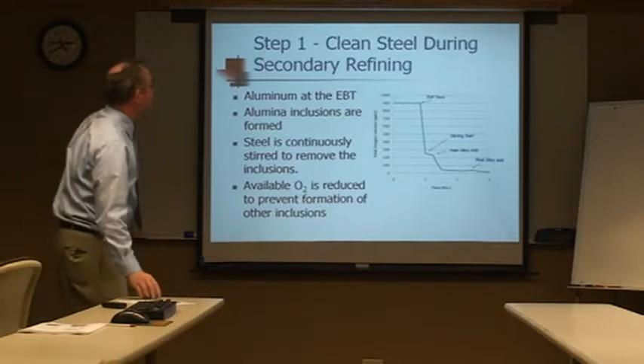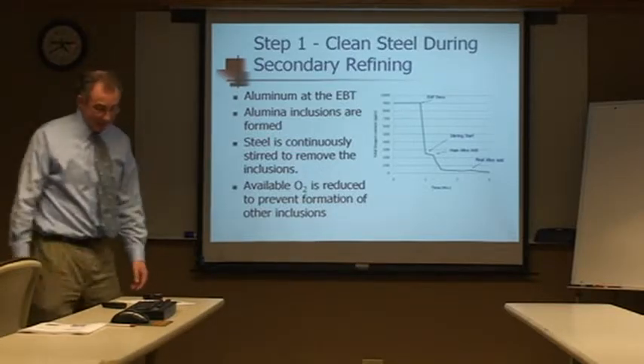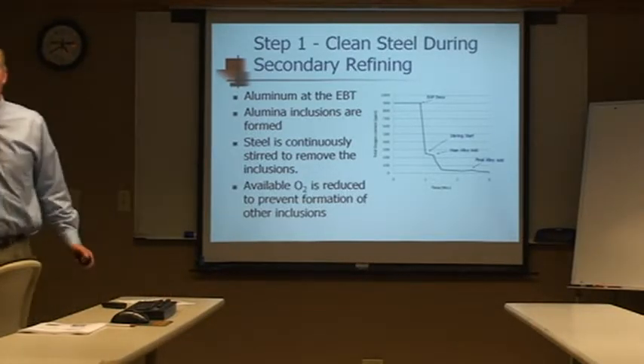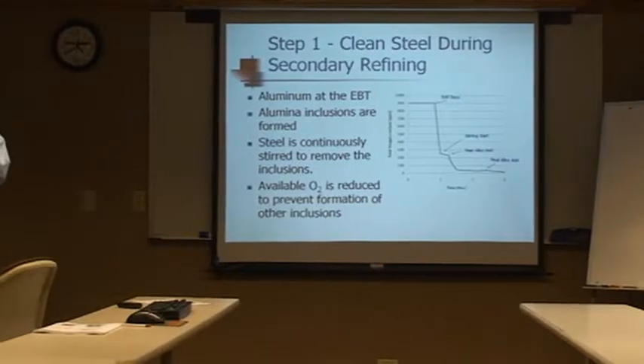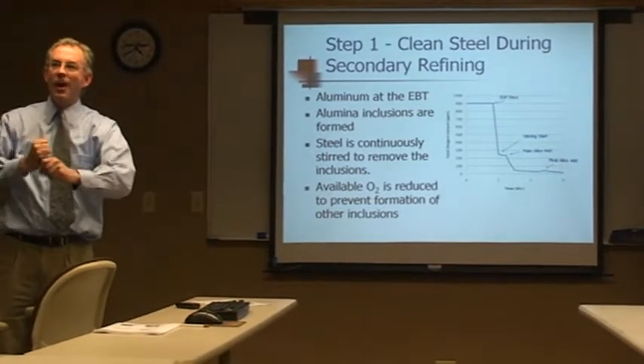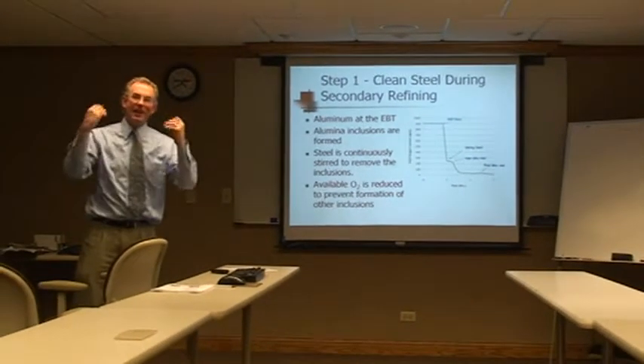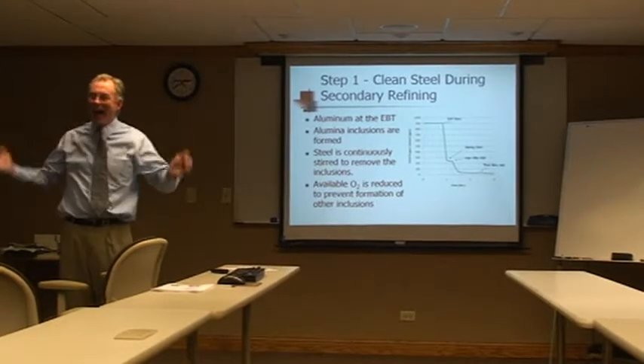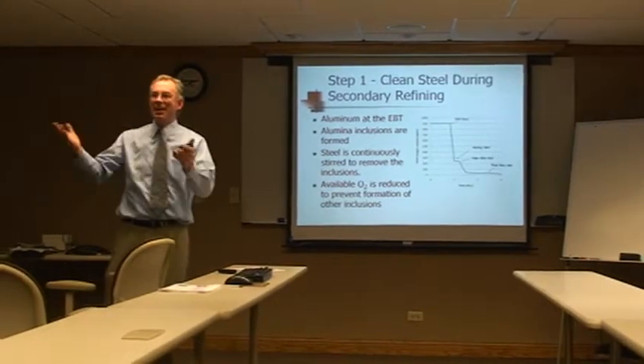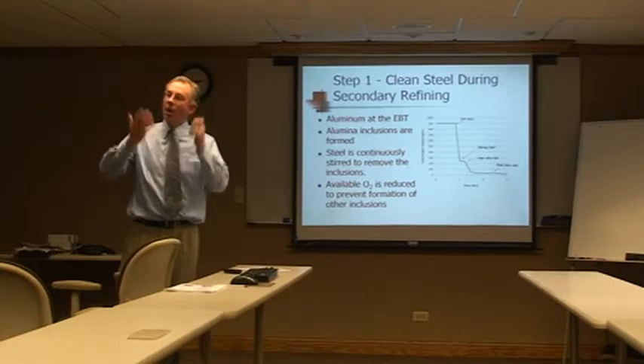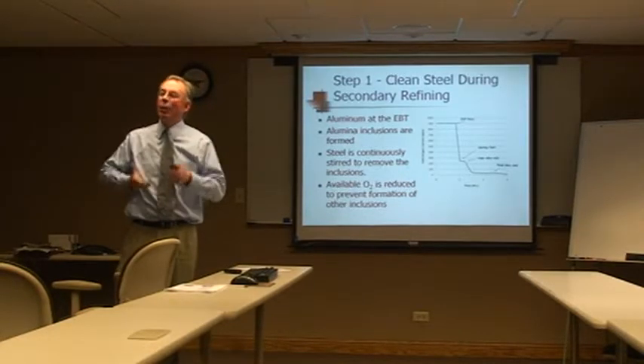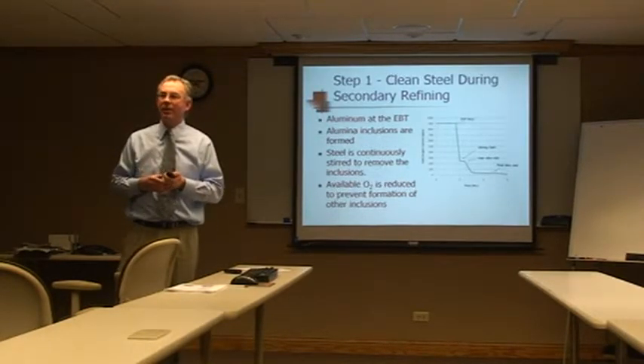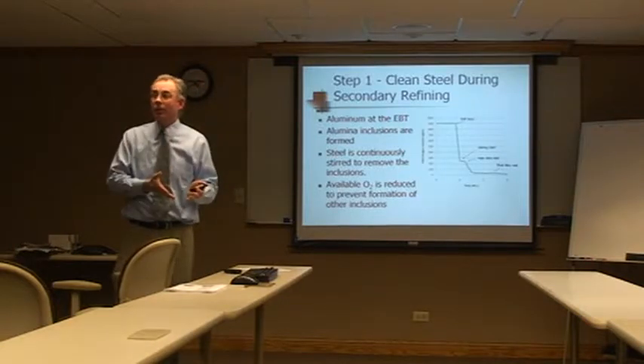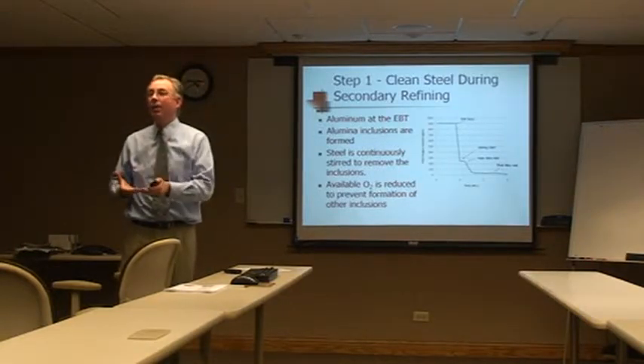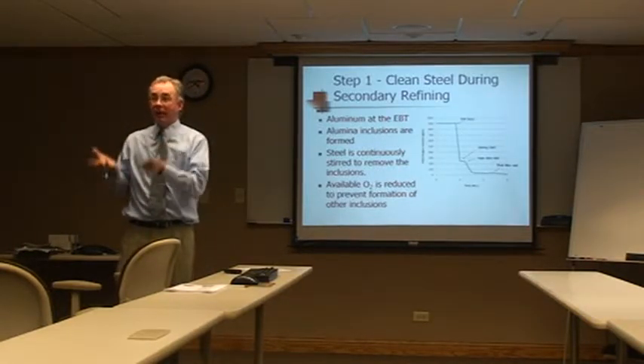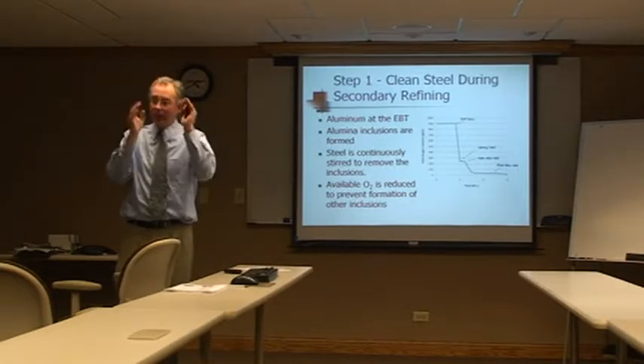So step 1, clean steel during secondary refining. If you remember back, in the arc furnace, we're blowing oxygen, right? We're blowing oxygen, we're getting rid of the carbon, we're getting this chemical heating, we're saving time, we're saving money, 20 minutes off of our tap-to-tap time. We got to tap that heat, we have 1,000 parts per million oxygen, okay? So number 1, we got to make sure that carbon's out of there, because if we tap with that much carbon and oxygen, we're going to get an explosion. So we get the carbon down.